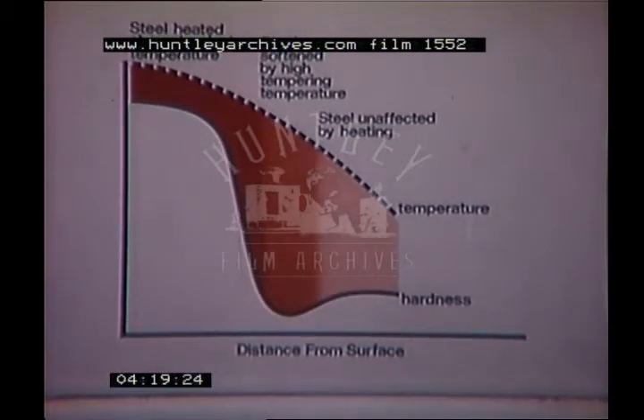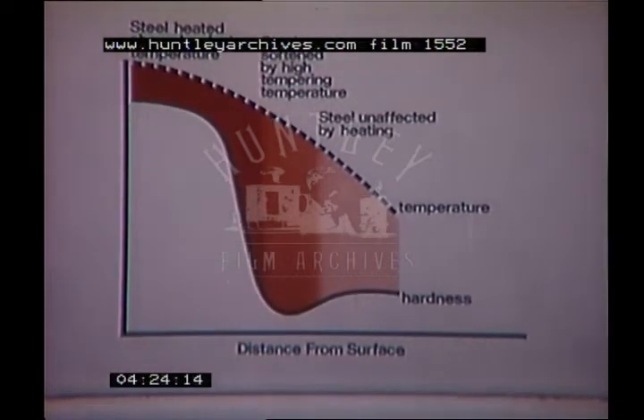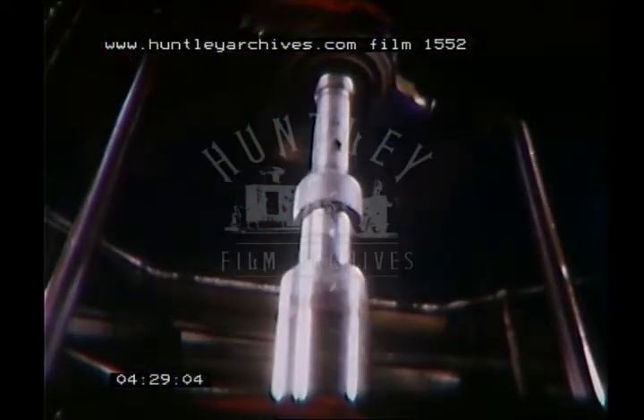Also, the need to use a high surface temperature to compensate for the short heating period can lead to coarse grain size and poor mechanical properties at the working surface. Spalls in induction hardened rolls can originate in this very soft region.